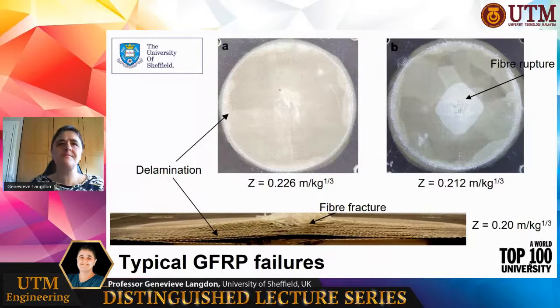and quite brittle. If you're new to FRPs, they differ significantly from materials like steel and aluminium because they have very little plastic capacity. And what that means is that they're brittle materials and that they will behave in an almost linear elastic way where the stress and strain will increase linearly. So stress increases linearly with strain until they get to the point where they fail. And then they fail in a brittle way, usually through cracking or matrix damage or something like that, or multiples of these kinds of failure modes. And that's what you can see on the screen here.